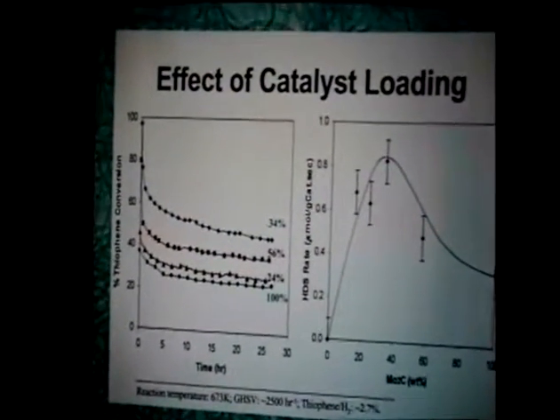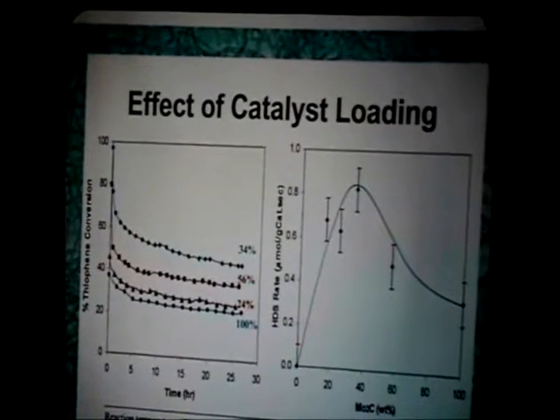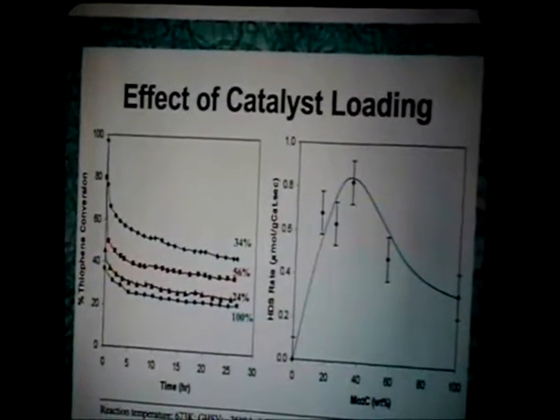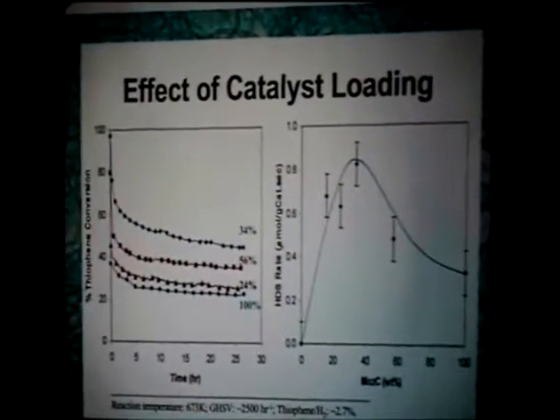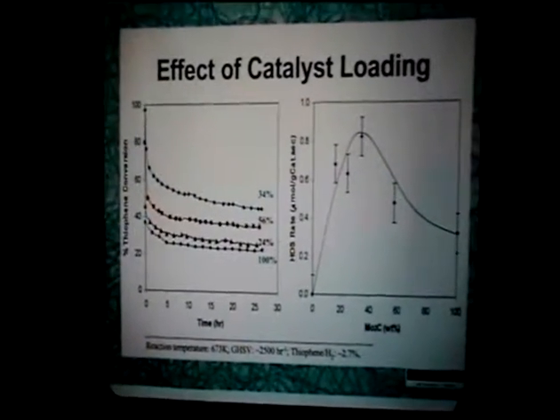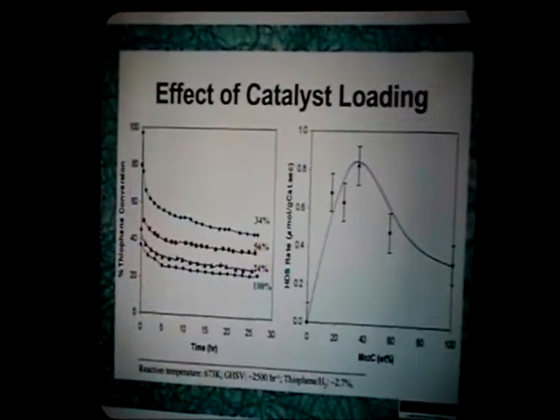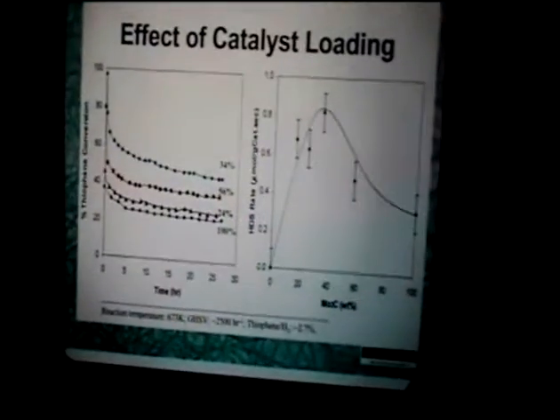And you see this volcano type of curve, and the reason for that is that when you increase the molybdenum carbide, you put more and more molybdenum carbide, of course, per gram, you're making more and more active sites, so the rate tends to go up. But if you pass a certain level, then you start destroying the structure, and then you have mostly bulk molybdenum carbide, and then you start decreasing the area. Remember, again, this is per gram of catalyst.